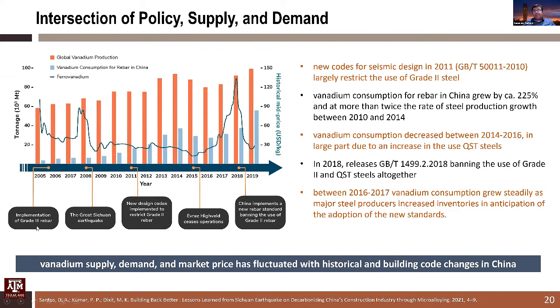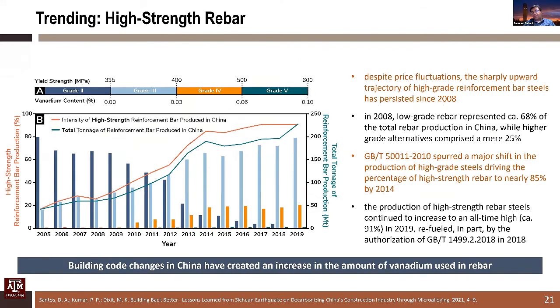If you look at the details here, the price spikes correlate with the implementation of the new rebar standard, and before that, the previous guidance on grade 3 rebar. So vanadium supply, demand, and market price has really fluctuated with historical building code changes. Much of this is driven by China, but this has also been a huge driver for the vanadium industry across the world, and this is a great thing. You can see here, as a result of code changes, grade 2 and grade 3 rebar, dark blue, almost completely being phased out, and grade 4, grade 5 rebar is increasing slowly, and this is again driven by the building code changes and the new building policies.